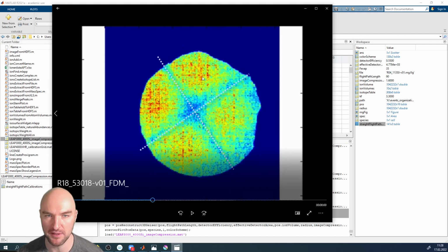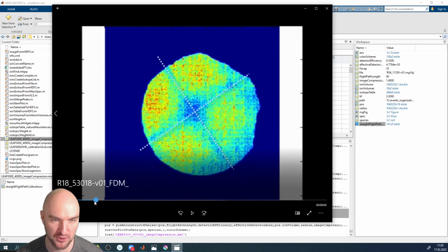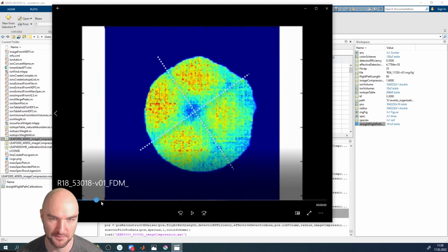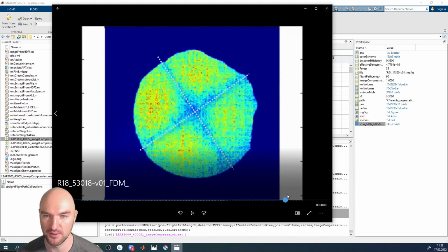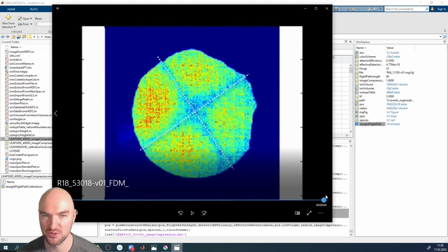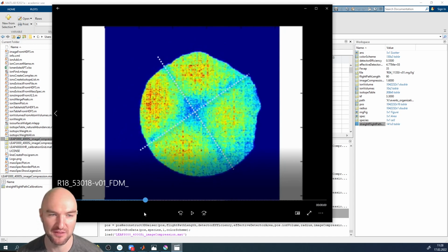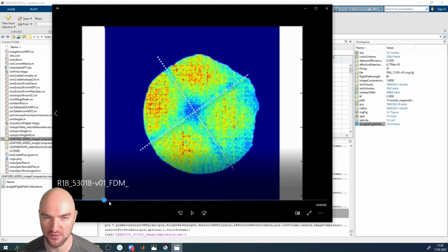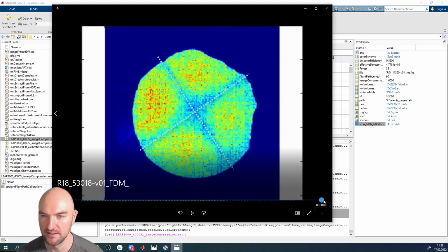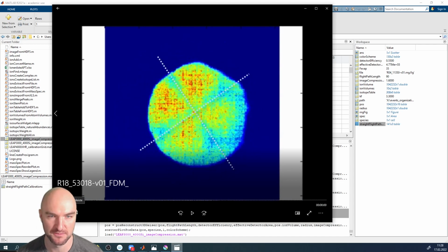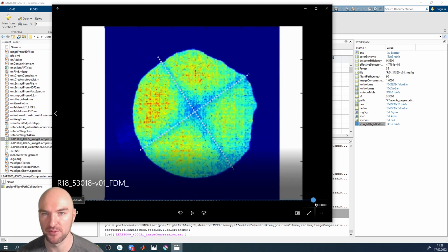All you need to do is maybe take one of those pre-sharpened posts, underfill a detector, and then just let it run, well, until it stops. You don't even need pulsing. You can just switch off pulsing your laser, no voltage pulsing. All you need is field evaporation, and then you can produce